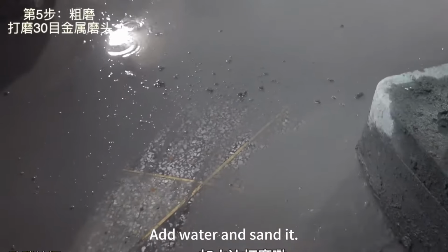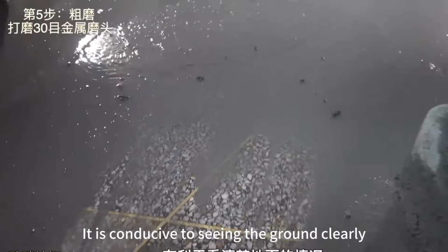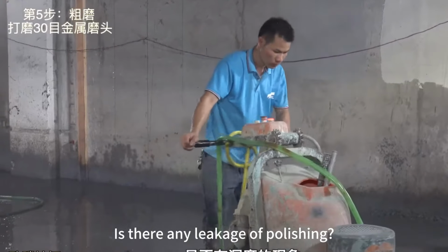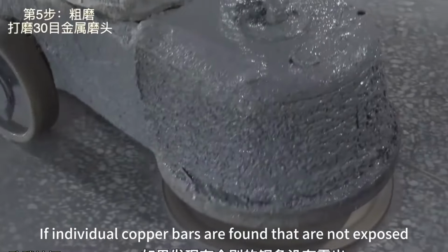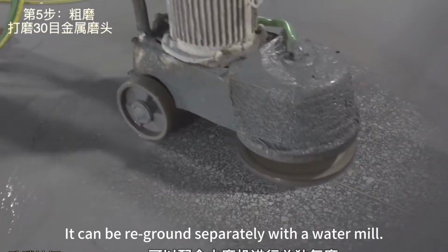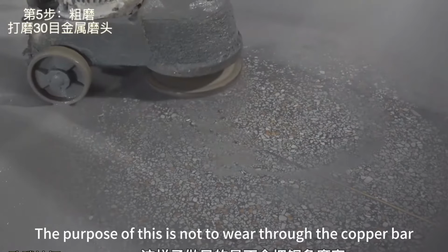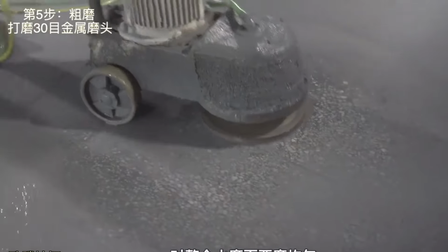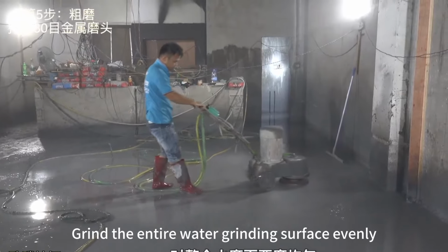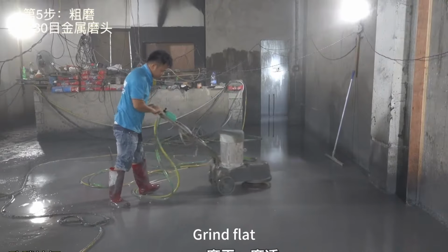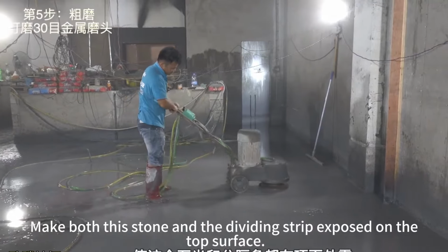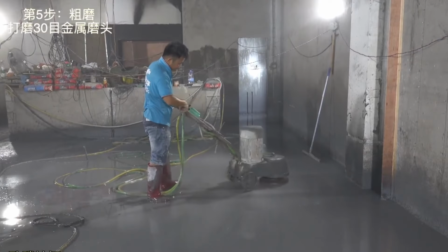When performing the second rough grinding, you can add water to polish. Add water and sand it. It is conducive to seeing the ground clearly. Is there any leakage of polishing? If individual copper bars are found that are not exposed, they can be reground separately with a water mill. The purpose of this is not to wear through the copper bar. Grind the entire water grinding surface evenly and flat. Make both this stone and the dividing strip exposed on the top surface.